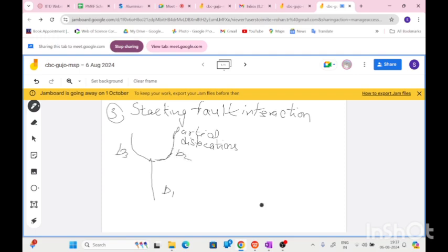So if solute atoms or alloying element atoms cluster around the stacking fault, that will hinder the motion of the dislocation, and the stacking fault will never be able to annihilate further. It cannot change into a single dislocation. So this clustering of alloying element at the stacking fault region increases the strength of the aluminum alloy. Higher stress will be required to remove the alloying elements and then to move the dislocation further.